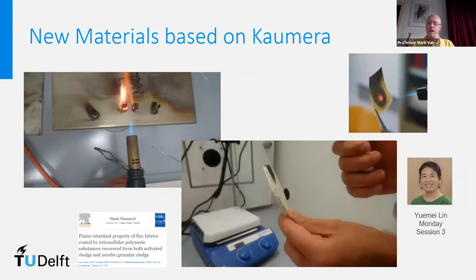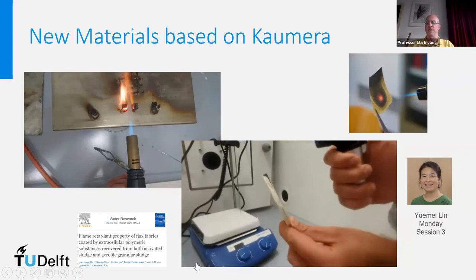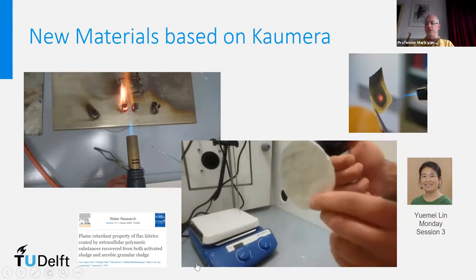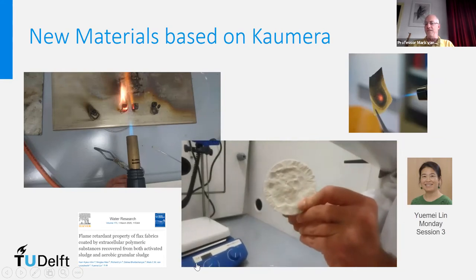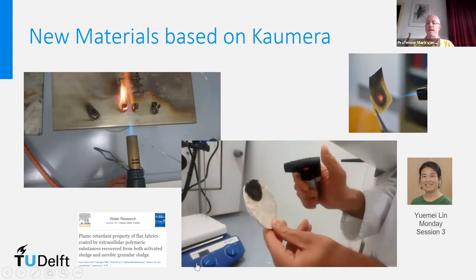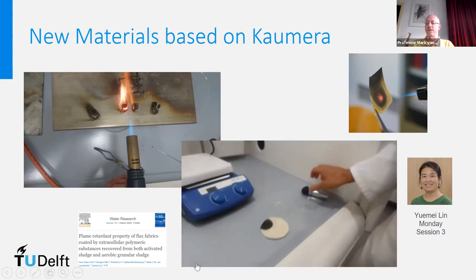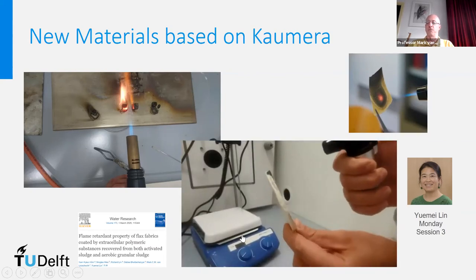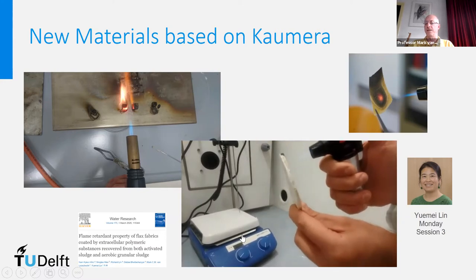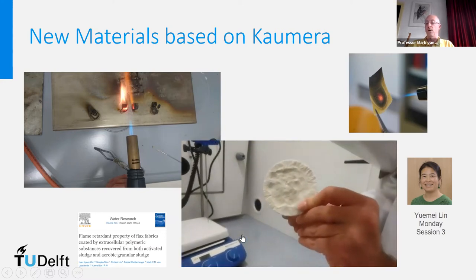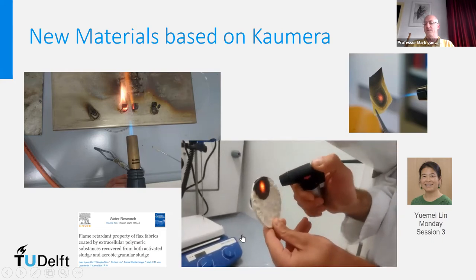Now, the other interesting application of the interesting capacity we saw from this is that we can make plastics out of the material, or foams, and they can be used in construction. And then, of course, the interesting thing is that in construction, flammability is important, and it is flame resistant without adding any flame retardant material. Normally, people would add, say, polybrominated or polyfluorinated materials. And on this picture, you will see that if you put a flame on the backside of this foam, there's no blackening, nothing becomes red, whereas the front side turns completely red.